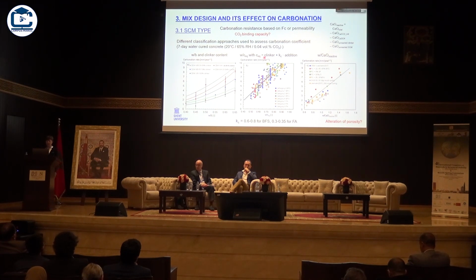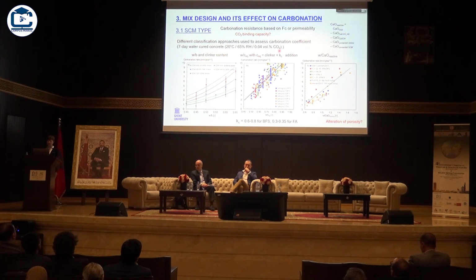Another way to consider this is that you just plot the water cement equivalent ratio, where you add your addition, actually your SCM, with a certain efficiency factor. And then this efficiency factor can be for slag, for instance, 0.6, 0.8, for fly ash around 0.3. And this then gives, but with quite some margins, a reasonable correlation.